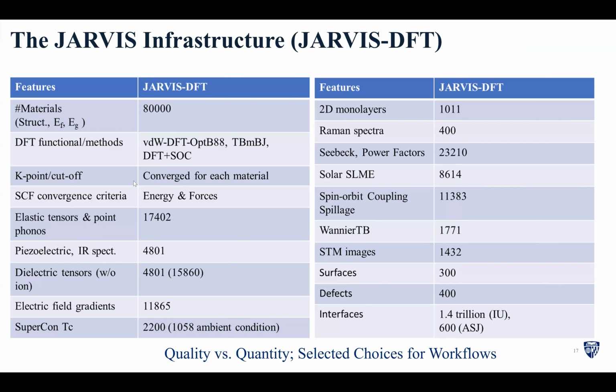We converge K-point and cutoff for each material automatically. We have a workflow for that. Of course, we had to make some choices. Nothing is perfect, but we have to make reasonable choices to be a part of a NIST website. So making this convergence renders the calculation about 5 to 10 times slower, but at the end, we can get reliable results. We also converge energy and forces.